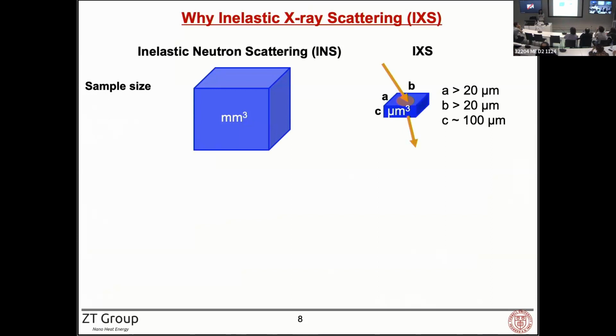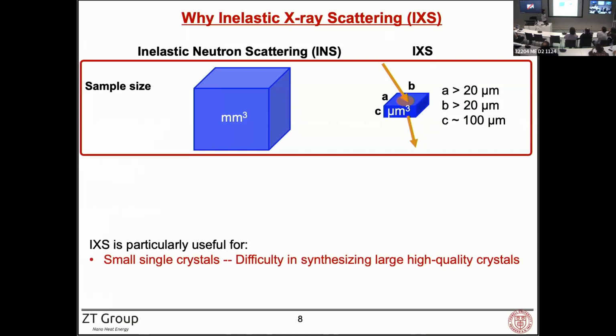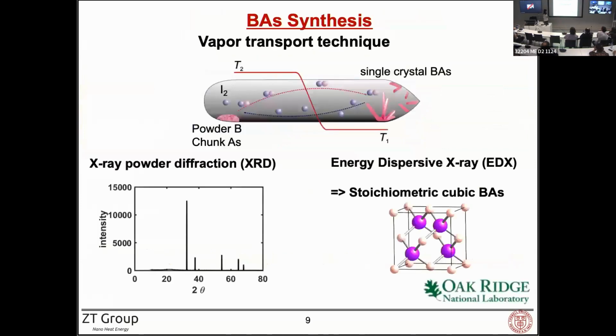This can be particularly useful if it's hard to grow high quality, large single crystals. And that is the case here. So we chose X-ray scattering for the phonon dispersion of cubic boron arsenide. We worked with collaborators at Oak Ridge National Lab. They synthesized the boron arsenide single crystals using the vapor transport technique, and they did the XRD and the EDX.